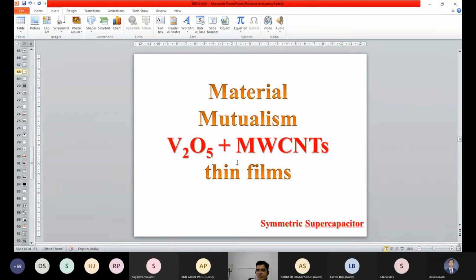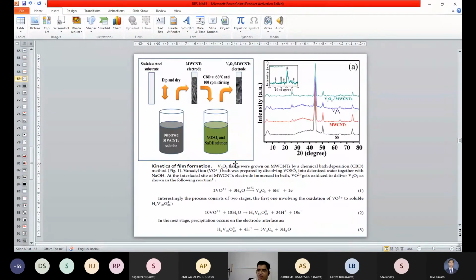The same vanadium we have used, right? But here we have formed the oxide, because oxides are much more stable than the sulfide or chalcogenide, we can say. And also here we have made a symmetric supercapacitor, but instead of SILAR, we have used chemical bath deposition. So what is chemical bath deposition? Inside this one, whatever the cation and anion, we are placing together inside one bath, inside one beaker, right? Simply you can have one beaker, you can place vanadium sulfate, you can place NaOH solution, right?